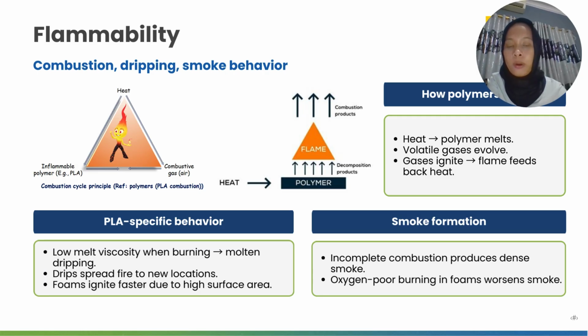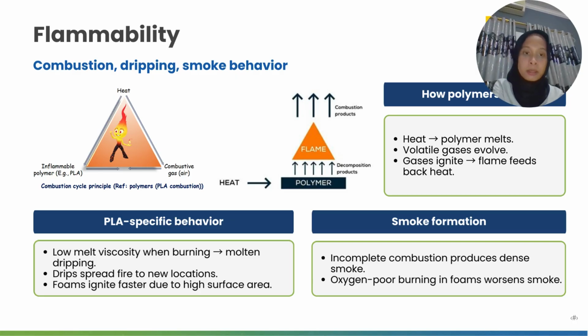Next is flammability: combustion, dripping, and smoke behavior. Why do polymers combust, drip, or smoke? Because heat makes the polymer melt and volatile gases evolve, and the gas ignites, and the flame feeds back heat. PLA-specific behavior is low melt viscosity when burning, which leads to molten dripping, and drips spread fire to new locations, and foams ignite faster due to the high surface area. In the smoke formation mechanism, incomplete combustion products make dense smoke, and oxygen-poor burning in foams worsens the smoke.